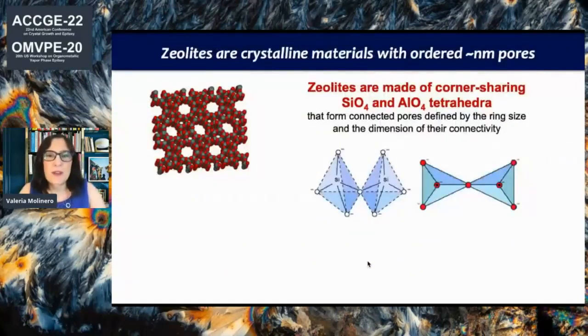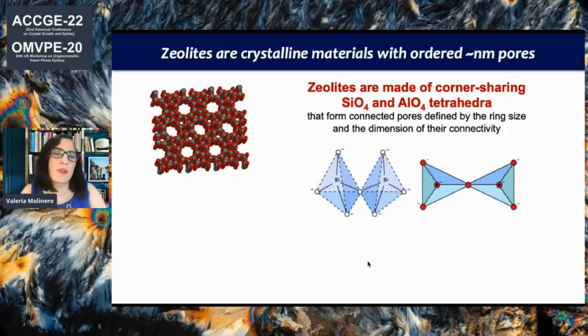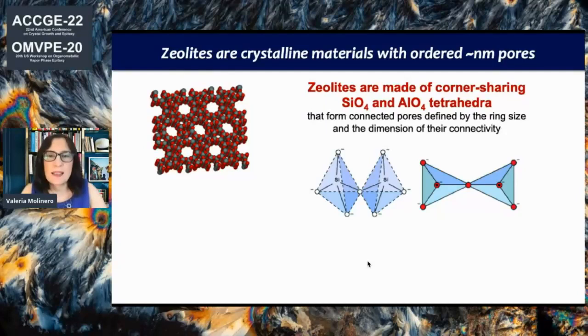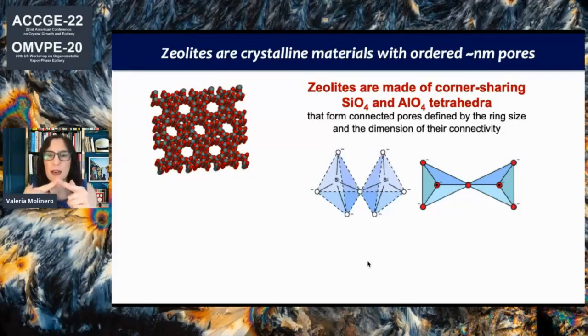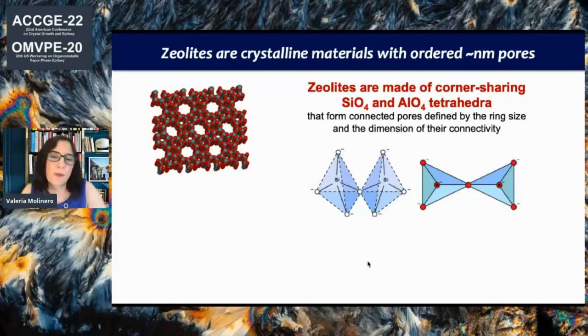When we think about zeolites, we have to consider that these are porous materials with very small pores — between a few Angstroms and nanometers. These zeolites are made of corner-sharing silica or alumina tetrahedra, and because there is so much flexibility in the angles they can form, there is a huge variety of polymorphs.